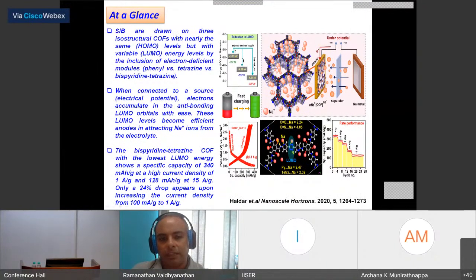So we have taken the modular approach to control the HOMO-LUMO gap of a COF. And then we have used such a COF to set up a driving force for sodium ions to load into it under a potential as an anode. And then we show that this can give rise to excellent rate performance and an excellent stability window for anodic material.